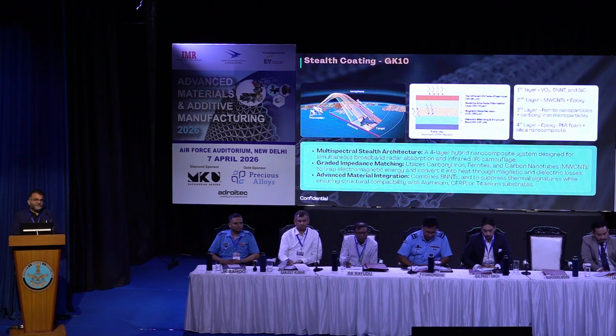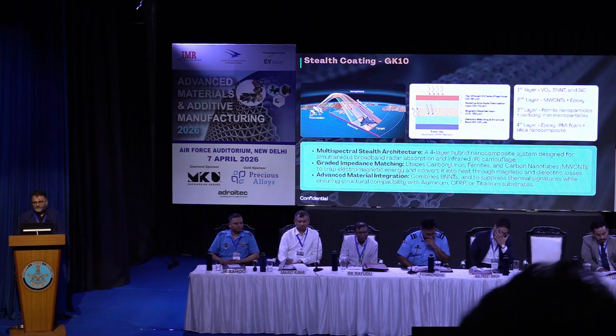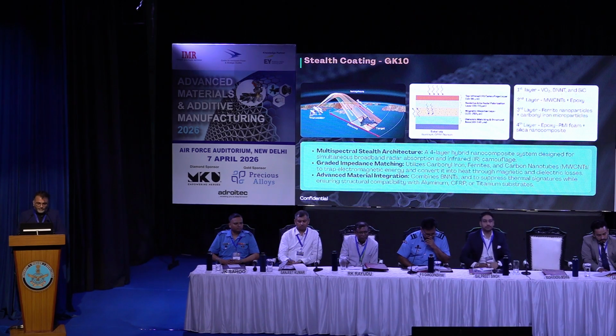So we started working on what materials are available. The classic ones are vanadium oxide, boron nitride nanotube, silicon carbide. There are 4 layers in the F-35 and B2 bombers, and they have different characteristics and coating techniques that are very difficult, but we were able to solve the 4 layers they are using. First is camouflage, that is IR camouflage. Second is resistive interfacial polarization, and third is the magnetic absorption layer. Fourth is the dielectric matching structure and base.